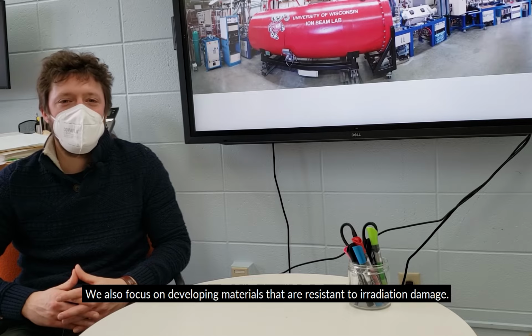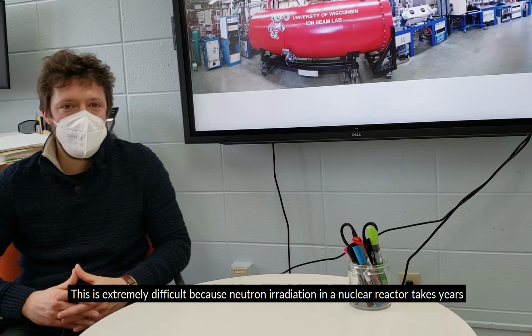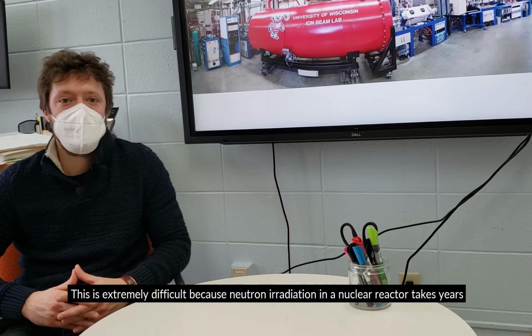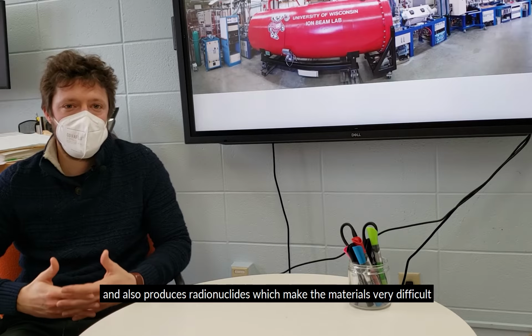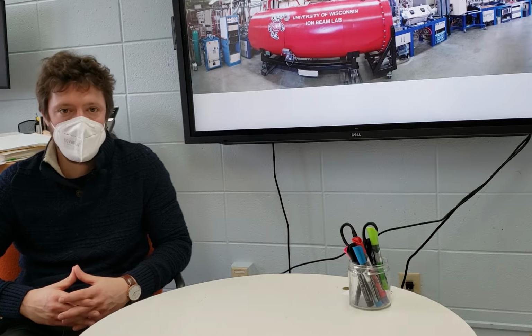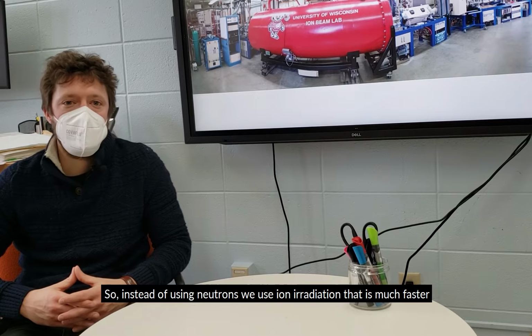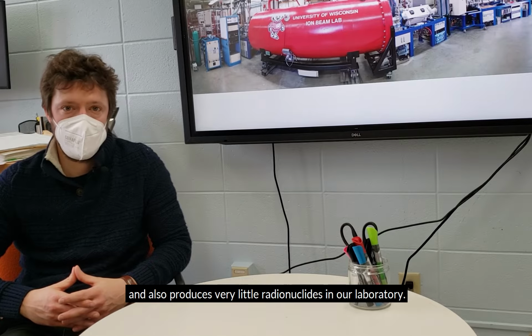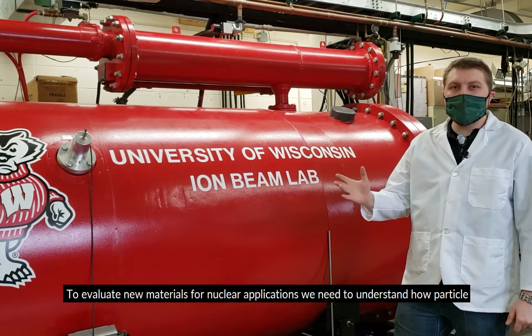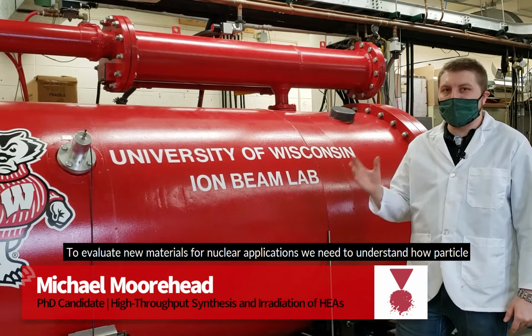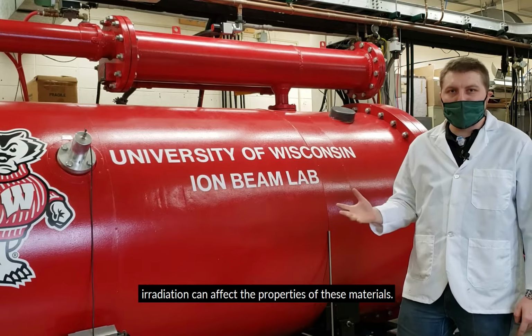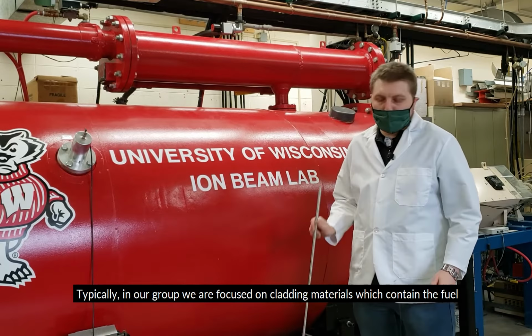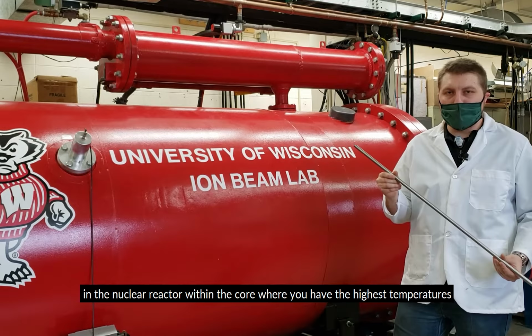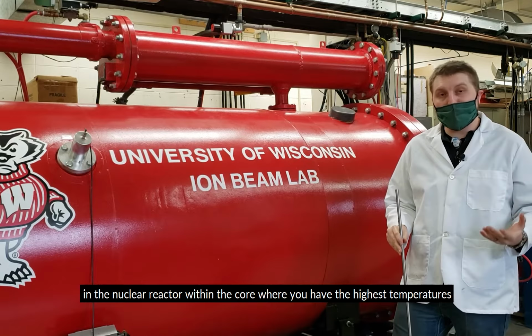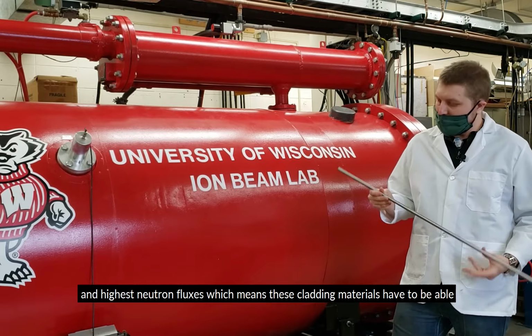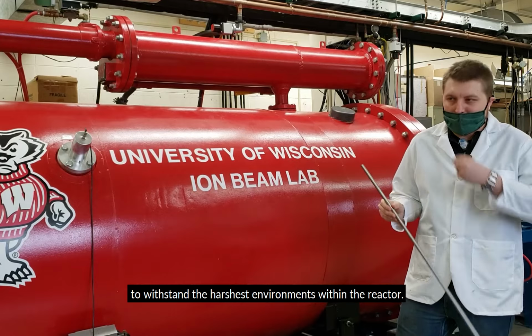We also focus on developing materials that are resistant to radiation damage. This is extremely difficult because neutron irradiation in nuclear reactors takes years and also produces radionuclides, which makes the materials very difficult to handle for characterization afterwards. So instead of using neutrons, we use ion irradiation that is much faster and also produces very little radionuclides in our laboratory. To evaluate new materials for nuclear applications, we need to understand how particle irradiation can affect the properties of these materials. Typically, in our group, we're focused on cladding materials which contain the fuel in the nuclear reactor within the core, where you have the highest temperatures and the highest neutron fluxes, which means that these cladding materials have to be able to withstand the harshest environments within the reactor.